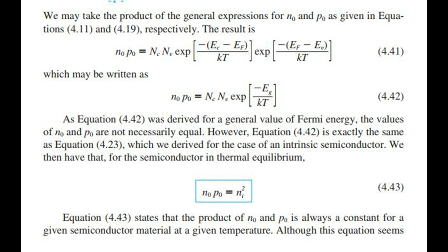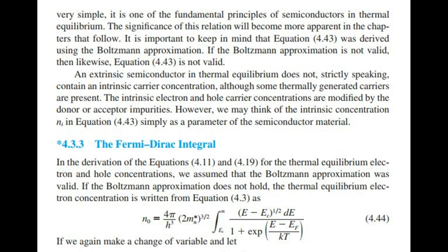We then have that, for the semiconductor in thermal equilibrium, equation 4.43 states that the product of N0 and P0 is always a constant for a given semiconductor material at a given temperature. Although this equation seems very simple, it is one of the fundamental principles of semiconductors in thermal equilibrium. The significance of this relation will become more apparent in the chapters that follow. It is important to keep in mind that equation 4.43 was derived using the Boltzmann approximation. If the Boltzmann approximation is not valid, then likewise, equation 4.43 is not valid.